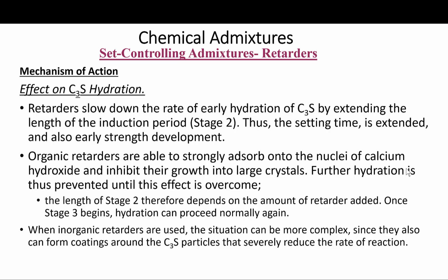When inorganic retarders are used, the situation can be more complex, since they can also form coatings around the C3S particles that severely reduce the rate of reaction. So again, you have to know what admixture is being used. This information really comes in handy in order to avoid any surprises later in your concrete mixes. You also need to remember this about extended set control: overdosing concrete with a retarding admixture